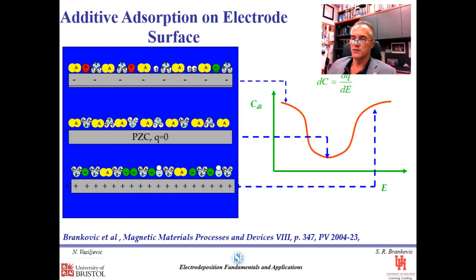To give you an idea, when we have an additive in the solution, or an organic material that we want to consider as an additive, at about the region of the PZC, close to that, we should see a capacitance swell with respect to the potential if we study this. And eventually, if we keep increasing the concentration of the additive, the capacitance swell will start to broaden out. That's a very good indication that our additive is adsorbing on the surface, which means it does what it's supposed to do. Now, if you go away from the PZC, in this direction or this direction, what happens is that additives are basically squeezed out by the charged particles, which compete with the charge on the electrode surface and try to counterbalance it.